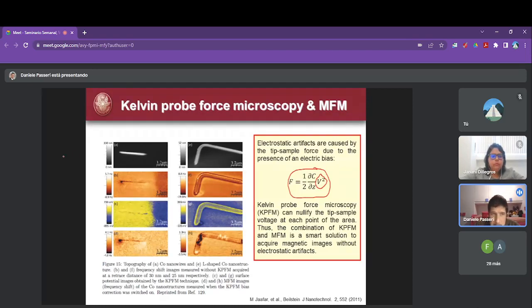And so what they did was, this is the topography. This is the standard magnetic force image. Now let's measure the surface potential. If you measure the surface potential, you can apply at every point of the image an opposite potential, so that locally the tip sample potential is 0. In this case, you nullify the electrostatic artifacts and you obtain the truly magnetic image. This is for a wire, a magnetic wire. This is for a more complex magnetic material.